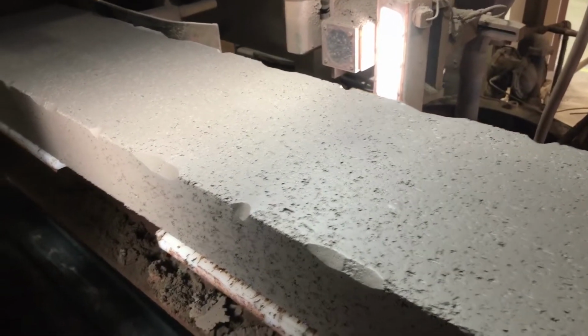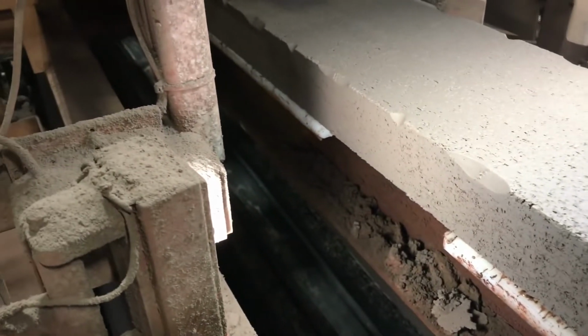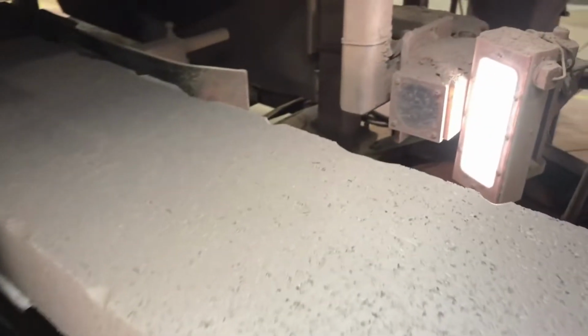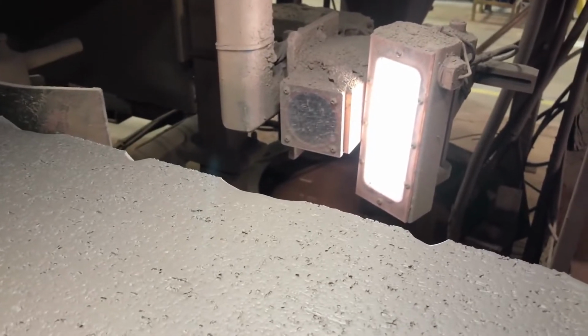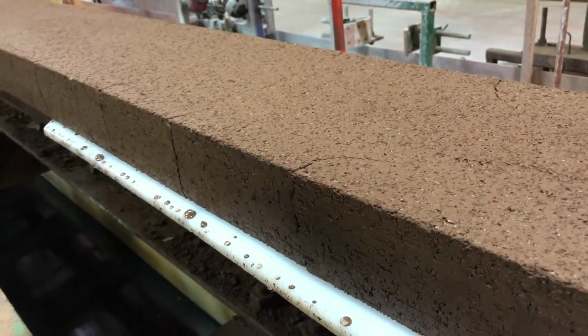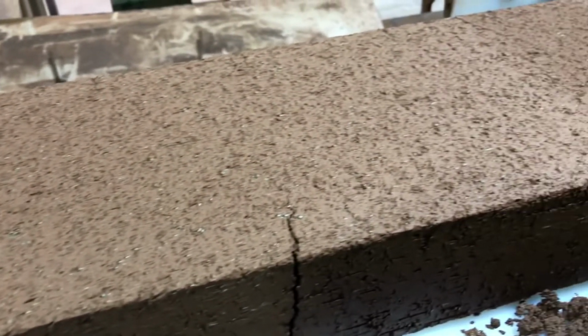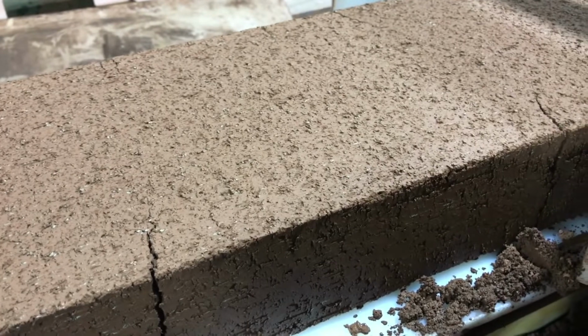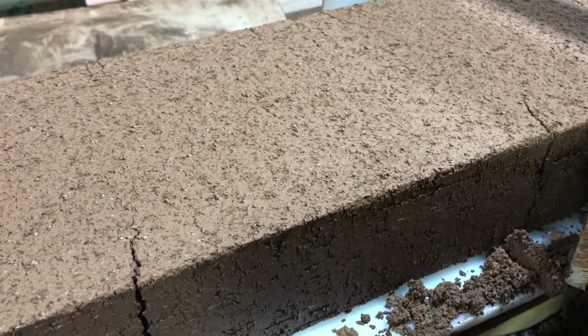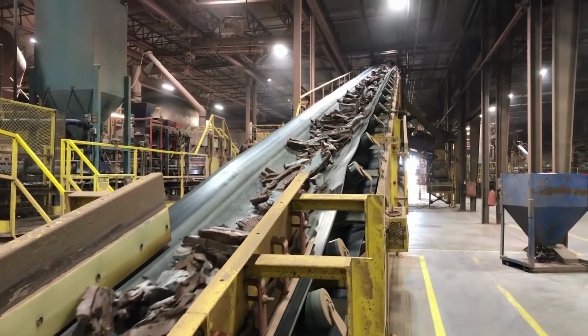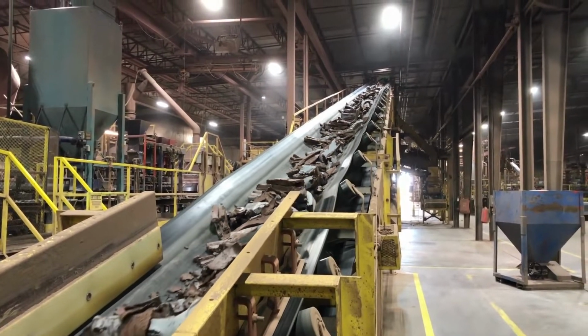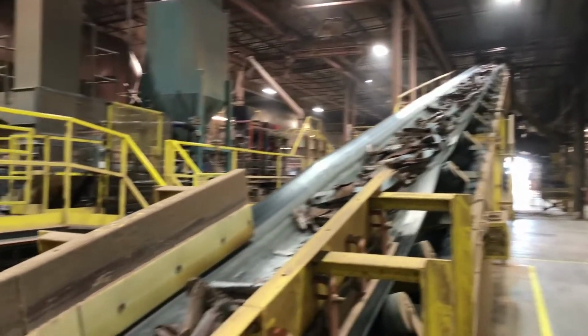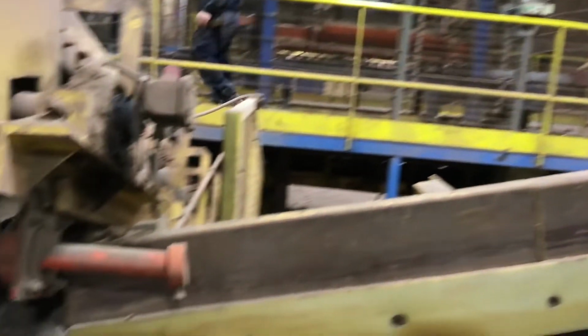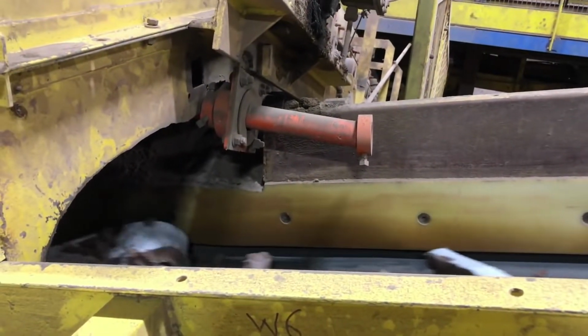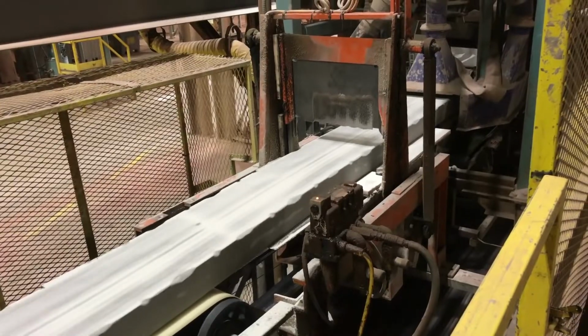This is an electric eye here that's measuring the coloring of the brick to make sure it's up to specs. Normally the extrusion would be whipping by, but it's stopped here, as I mentioned, for a few minutes, and I can get a look at that. Now, a little while later, the line was still stopped, and the clay started to dry out. So we see some cracks there, which means that this whole run is more or less useless. So when the plant fired back up again, all those cracked chunks were broken up and sent by this conveyor back to that grinding facility that I told you about initially.